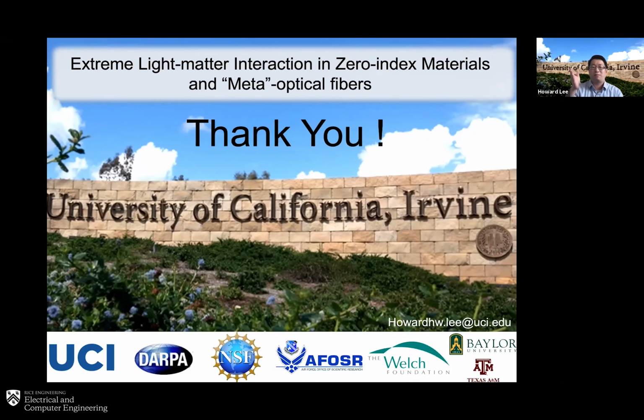But just keep in mind, for example, even metal, like silver, has a crossing point as well, so you can also have an ENZ property or ENZ mode. But because your ENZ is in the UV range, that means you need to make the thin film really thin, maybe a few nanometers, in order to excite this mode. But you can also support ENZ mode in metal as well. Okay, so is it sort of similar maybe to a gap plasmon type?